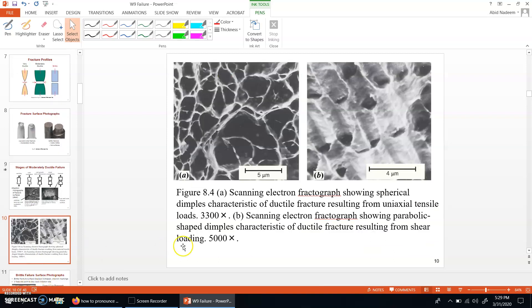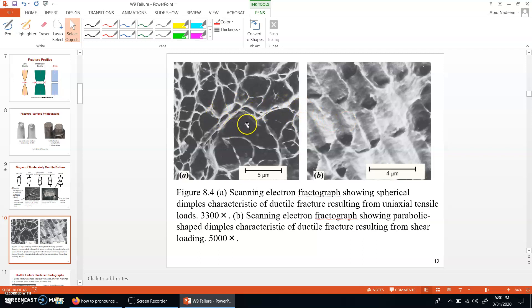Next are the fractographs, which are basically the SEM images of fractured surfaces. Two types of fractured surfaces can be observed in ductile material. One shows spherical dimples — spherical surfaces — for the inner part of the fracture surface. At the outer layers of the fracture surface, you may have some elongated parabolic-shaped dimples due to shear loading along those areas.